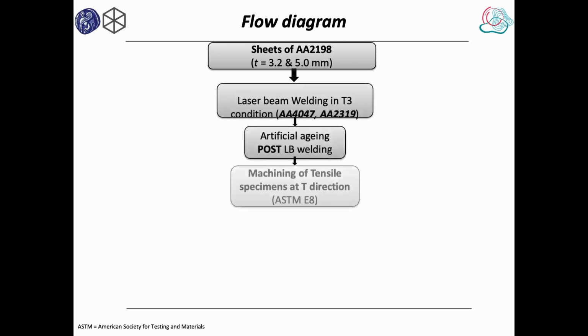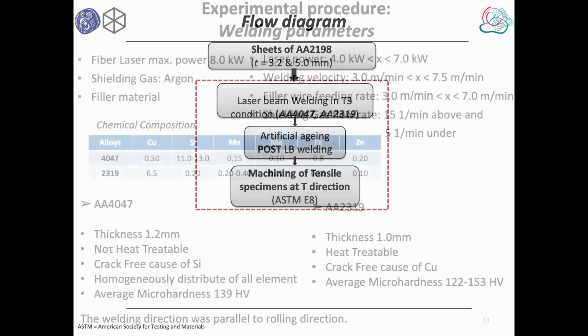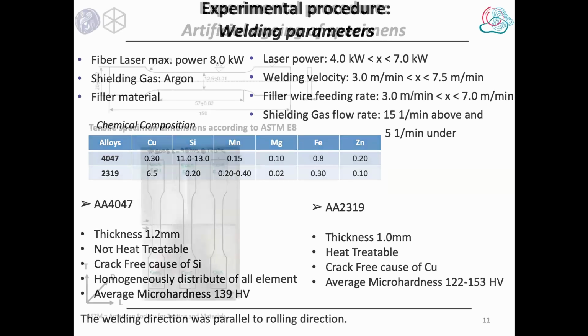And we investigated welding for the material 2198 with two thicknesses, 3.2 and 5 millimeter. And during welding, we also investigated the effect of different wires. The typical wire is the high silicon content alloy 4047. And in our work, we also considered a wire with copper as a base alloying element. And we performed optimization with regard to welding, and we investigated different heat treatment conditions after welding.